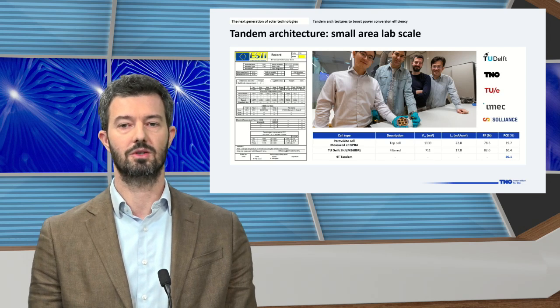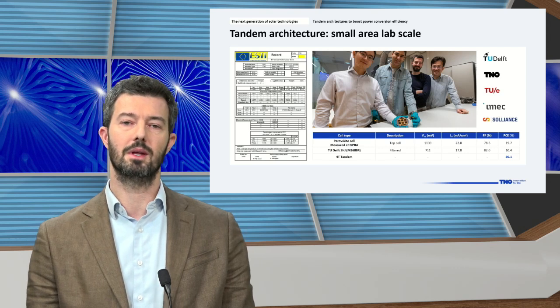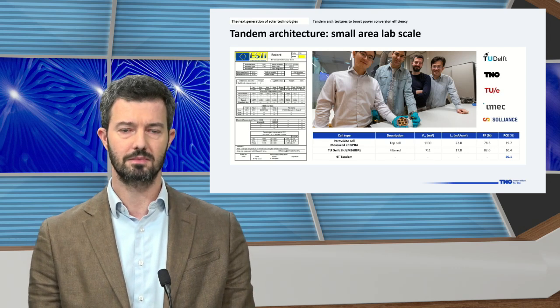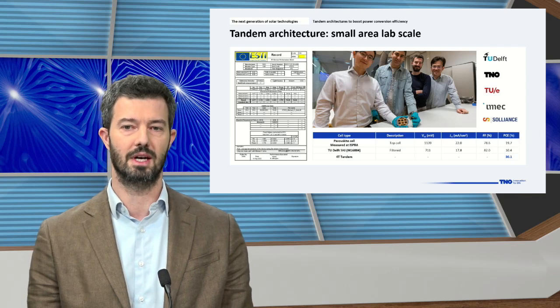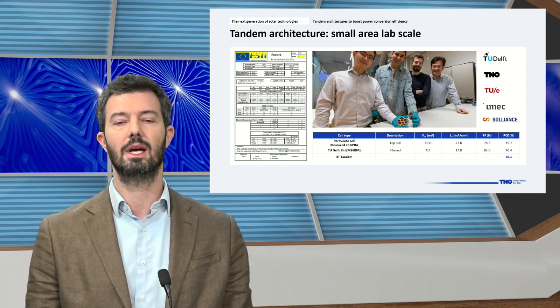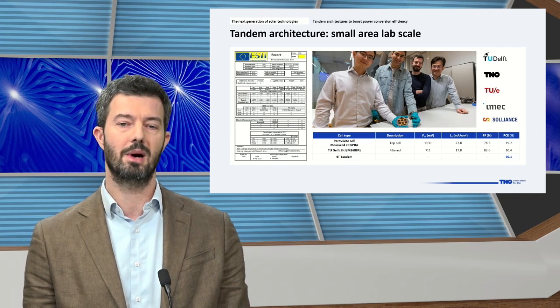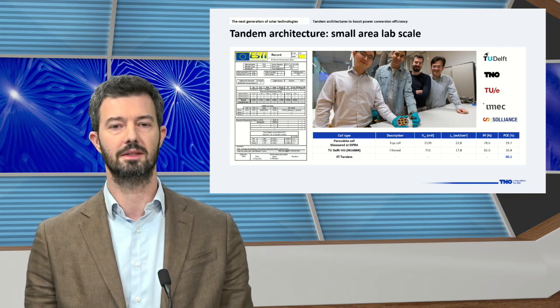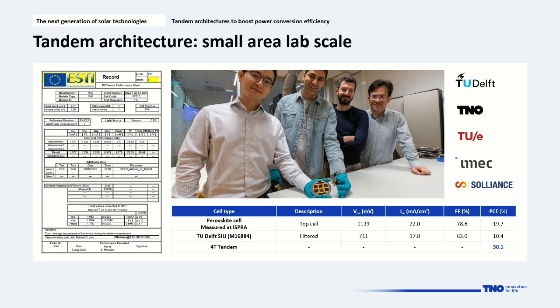And with this cell, in the range of 20% after certification, we combined with a silicon heterojunction provided by our partner TU Delft with an initial efficiency of, I think, 24%. And we calculated a 4-terminal power conversion efficiency of 30%. I think this was the first example for a tandem architecture breaking the milestone of 30%, and it's also kind of a psychological barrier for the community.